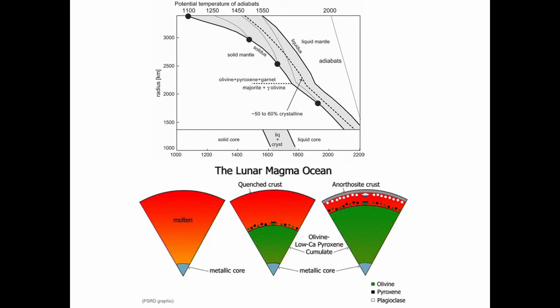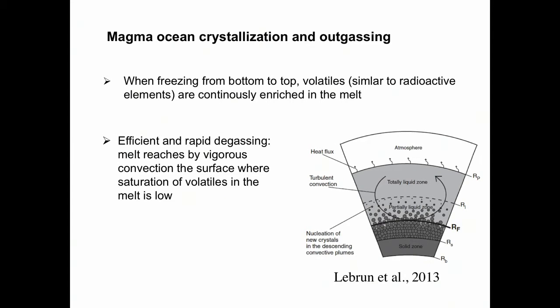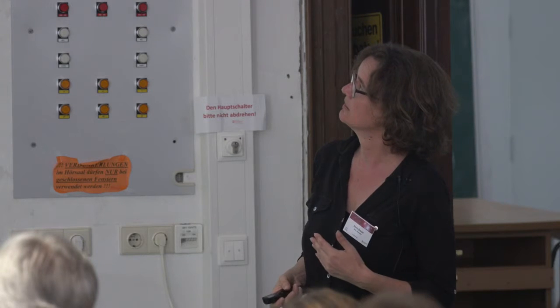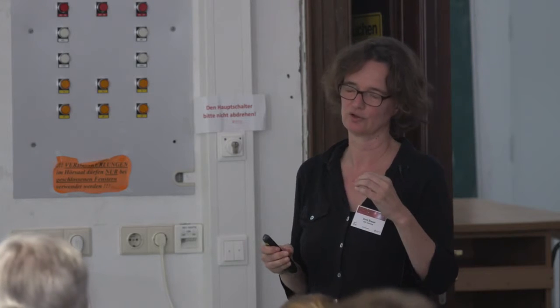Okay, but why is all that important for our question about the volatiles? So what we have seen before is that we have a density profile which is unstable. And what is it all about with outgassing and with water? Similar to iron, which enriches into the melt and crystallizes at the end, it's the same with the volatiles, or with the radioactive elements. So if you start crystallizing silicates, they take only a little bit of radioactive heat sources, and also a little bit of volatiles, of water. That's because the partition coefficient is very small. So if you have melt that starts crystallizing, only a tiny bit goes into the solid part, the rest stays in the liquid part.